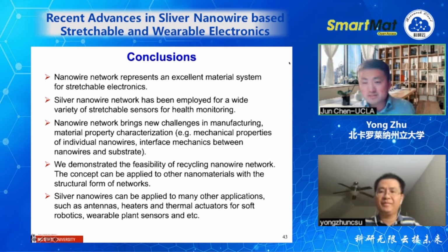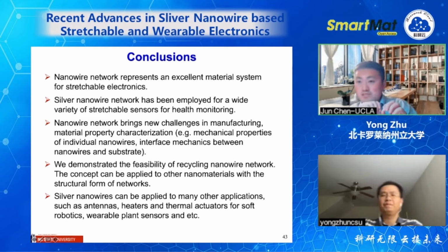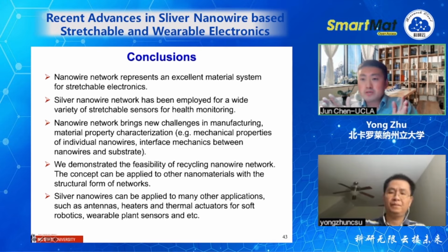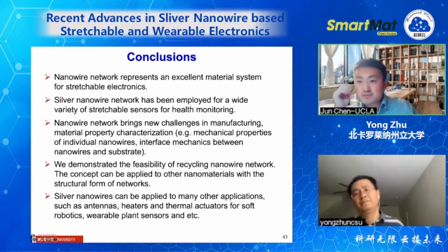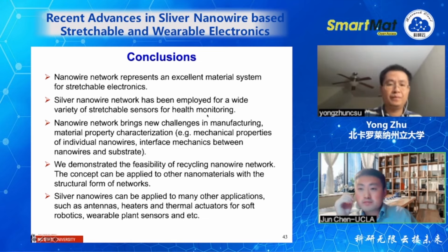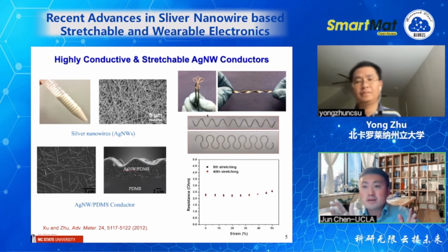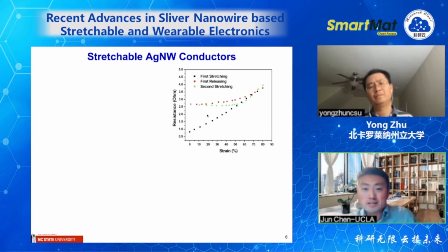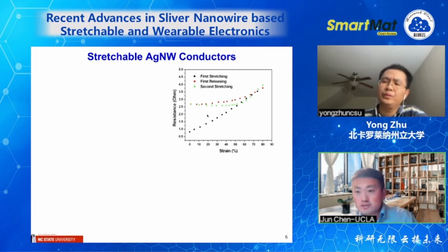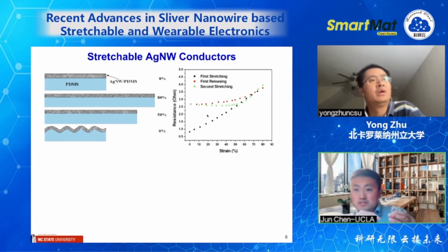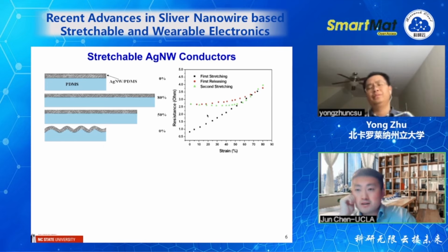So here's the first question. In your stretching test of silver nanowire, you show in the first stretch and second stretch they have a resistance change, especially before the strain is smaller than 50%, right? In your very first slides, showing when you stretch the first stretch and second stretch, you can see the resistance change increase a little bit for the second stretch. So the audience wanted to ask whether the silver nanowire length and concentration matter for this kind of performance, I mean the difference between the initial stretch and the second stretch, or whether this is just constant performance for all of the silver nanowire-based composites.